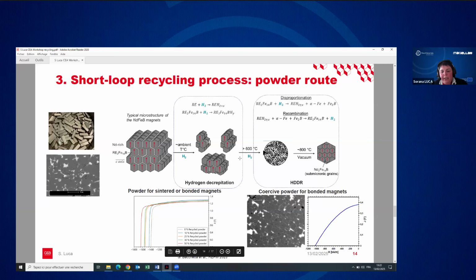At higher temperature, under hydrogen above 600 degrees, the magnetic phase will disproportionate. However, this reaction is reversible, because under vacuum, the neodymium iron and iron boron will recombine to form submicronic grains into a large particle. So this powder is coercive and can be used for bonded magnets. Here you can see the microstructure of a particle, and inside, submicronic grains of neodymium-2 iron 14 boron.